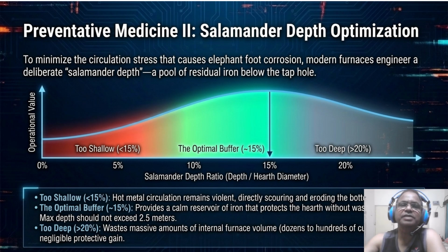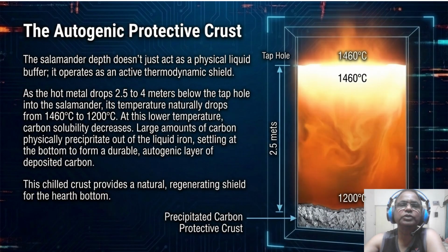So coming to our next slide, which is about the autogenic protective crust. So the salamander depth is not just a physical buffer, it's an active thermodynamic shield. So look at the temperature on the hearth. As the hot metal drops 2.5 to 4 meters below the tap hole, its temperature naturally drops from 1460 to 1200 degrees Celsius. So at this lower temperature, carbon solubility decreases. What happens next? Beautiful engineering.